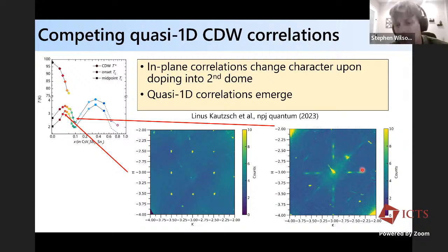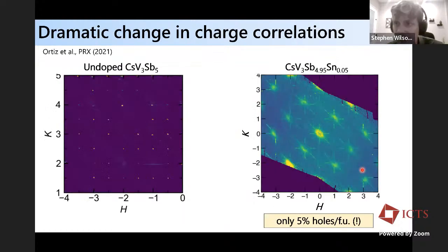Okay, and so in a 3-domain model, this would be quasi one-dimensional correlations because they also become diffuse out of the plane. And since there's not a ton of scattering work, I just want to emphasize how different the scattering looks between the undoped system, the parent cesium vanadium 3 antimony 5 system, and the slightly doped one, which is 5%. So this is only 5% holes per formula unit. So it's a reasonably small perturbation to the chemistry of the system, and you can see the dramatic change in the charge correlations, okay? And so in our picture, we're pushing this close to what seems to be a nearby 1D instability where the charge correlations become incommensurate as the lattice instability is suppressed in the 2 by 2 charge density wave phase.